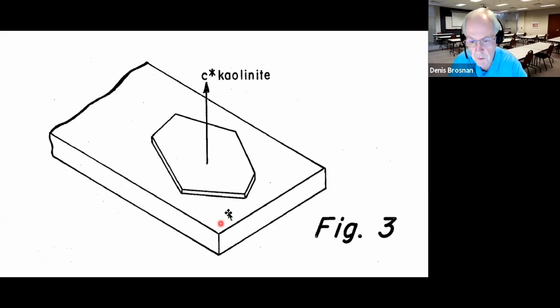He said that within any individual cell wall, because we're extruding this, the kaolin crystals, which are plate-like in nature, are going to line up. So their basal plane is aligned parallel to the direction of extrusion. So this is a wonderful idea. And it would be great if we could get all of them to line up in the direction of extrusion. We can't do that because we have different particle sizes and we don't reach a dynamic equilibrium in extruding a small article. But nevertheless,